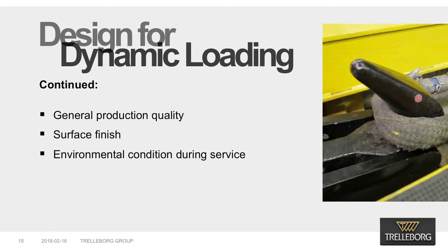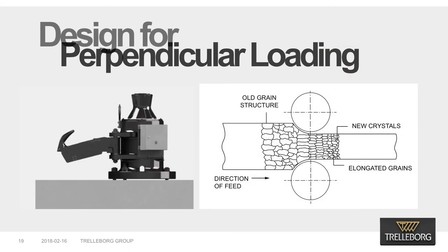Our design and manufacturing process pays specific attention to highly stressed spots, improving fatigue resistance and leading to extended product life, ultimately producing a better investment. As well as dynamic loading, mooring fittings are subject to perpendicular loading across many components, especially at the base plate and the clevis holding the quick-release hook. Rolled plates are not the ideal solution to sustain perpendicular loading. The rolling process causes elongation of the grain, resulting in anisotropic properties of the steel plates, which makes them less able to sustain load in the direction perpendicular to the grain structure. When loaded perpendicularly, welded plates may exhibit cracks parallel to the grain direction, called lamellar tear.